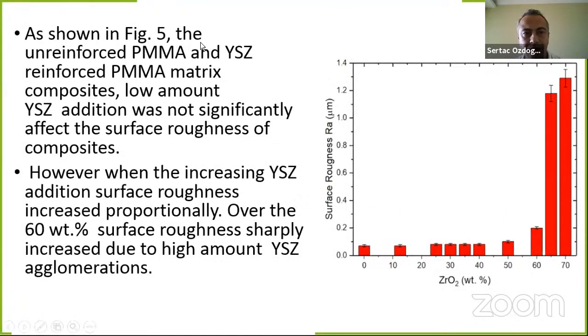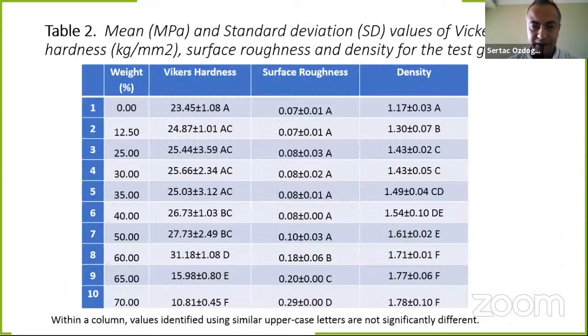Also shown in figure 5, for the unreinforced polymethyl methacrylate and yttria-stabilized zirconia reinforced polymethyl methacrylate matrix composite, low amount addition didn't significantly affect surface roughness. However, with increasing powder addition, surface roughness increased proportionally. Over 60%, surface roughness sharply increased due to the high amount of yttria-stabilized zirconia agglomerations. And we can see the values and statistical comparisons of the powder additions.